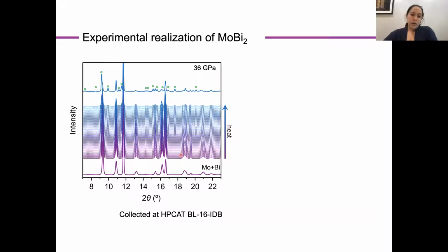And hopefully you can see here that by the time we turn on the lasers and get to this pattern here, we start to see the formations of new peaks growing in. So that corresponds to about 1400 Kelvin in terms of temperature conditions. And we can watch how these peaks evolve as we play around with the temperature to try to push the reaction towards completion. And we end up with beautiful diffraction patterns at the end that look like this, with the new peaks highlighted with these green dots.